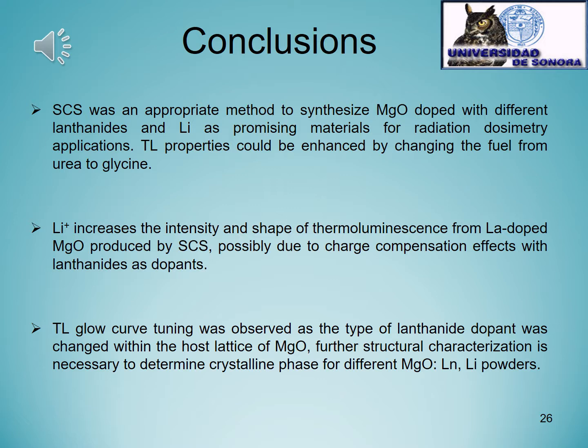Also to see not only the role of lithium but also, by X-ray photoelectron spectroscopy, to see the chemical environment of lithium, to detect this ion and see exactly not just the effect but the specific position lithium has within the crystal structure of magnesium oxide.